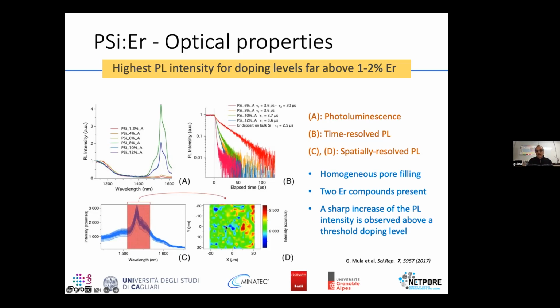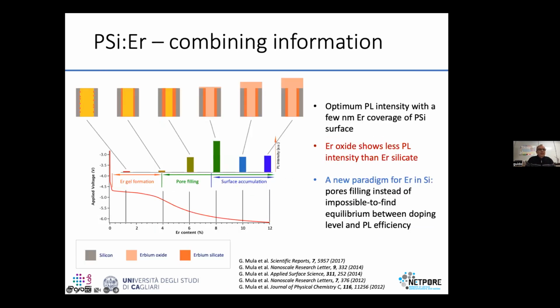So what happens when you combine all this information together? You can see here the full extension of the applied voltage versus erbium content behavior, where you have the first two transients I described before, and the third transient, which is much slower than the first two. And the photoluminescence intensity is this colored bar. In the first part, you have the erbium gel formation where the solution densifies and you start to deposit some nanoparticles on the walls that later on become a full coverage. And then your emission intensity rises significantly just when you start to really fill your pores, with the thickening or the coverage of the pore wall.